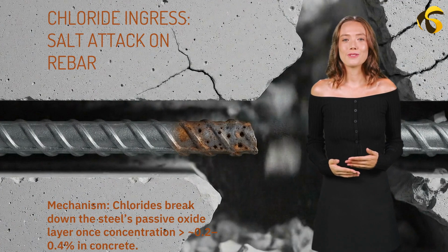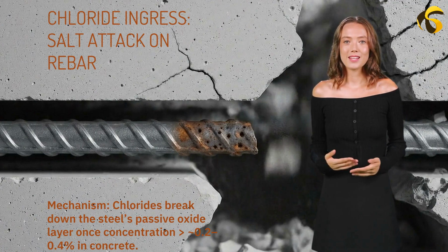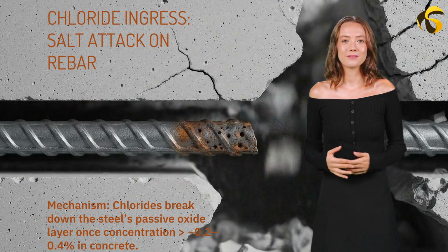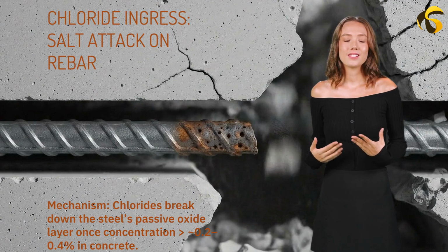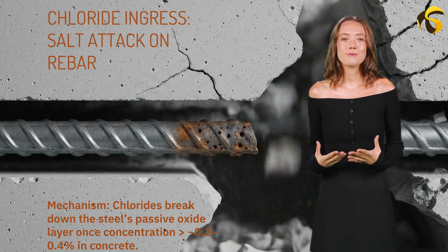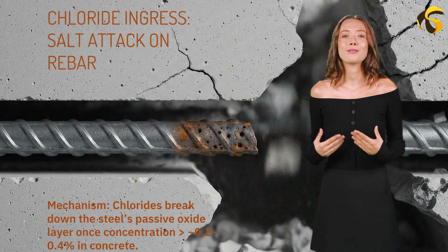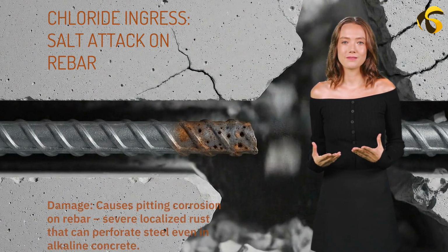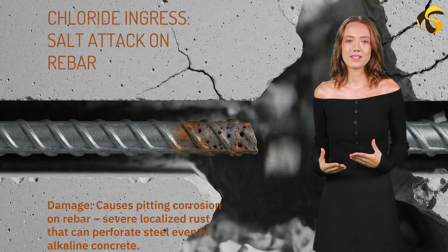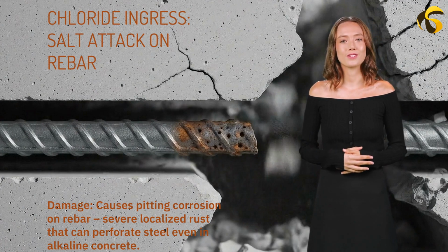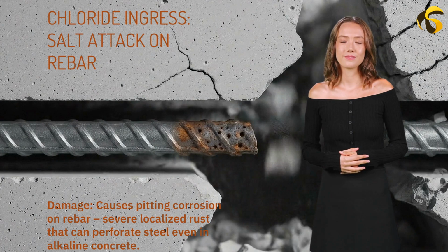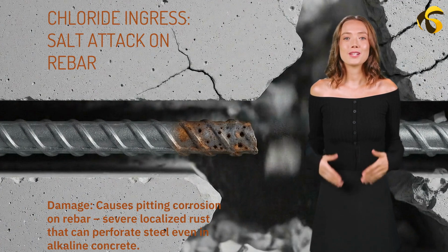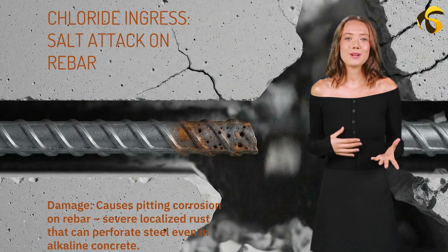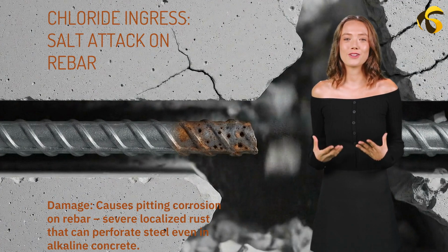What follows is pitting corrosion, very localized, pinpoint rusting of the rebar that can eat holes into the steel. Unlike uniform corrosion, pitting from chlorides is insidious. The steel can look fine on the outside, but have deep pits weakening its cross-section. Chlorides also turbocharge the corrosion reaction, leading to much faster rust formation. Even in a high pH environment, chlorides can trigger corrosion at specific spots. This is why a salt-exposed structure, like a bridge by the coast or a parking garage with winter salt, might see rebar failure much sooner than expected.